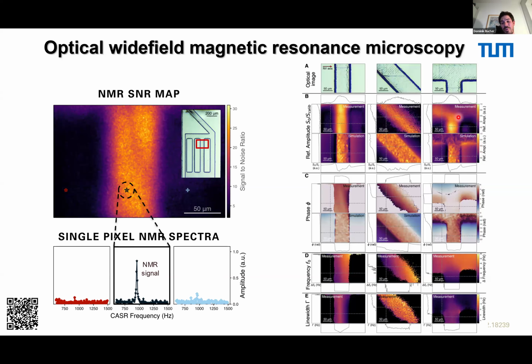Again, the most important point for NMR is you can not only look at the water intensity and the signal intensity, but also at the phase of the NMR signal, where you see some interesting geometry effects, but also the frequency and also the line width, which gives you information about local magnetic field gradients, and of course in the long term also to see really spectra to do chemical analysis in a highly parallelized way.